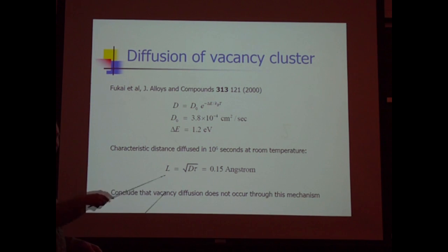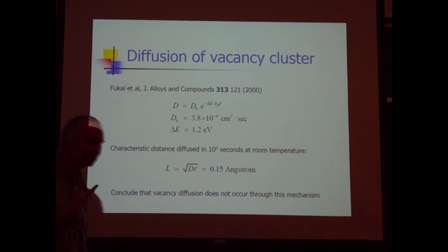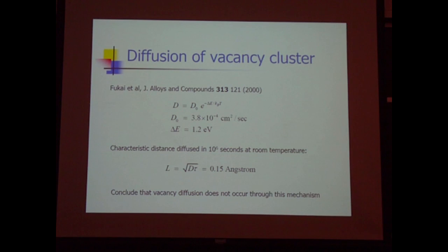We're facing this, which basically says the vacancies can't move in a time scale relevant to the experiment at near room temperature. So we don't do any good. So loading to 0.95 at the moment, which could make the Fukai phase, isn't going to make the Fukai phase. So we're looking at this, so much promise in the approach, and we're shot down. It doesn't work.